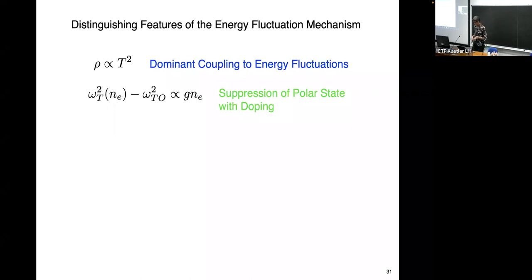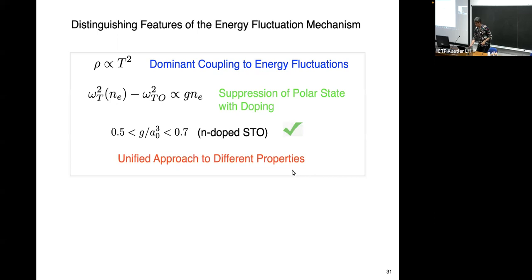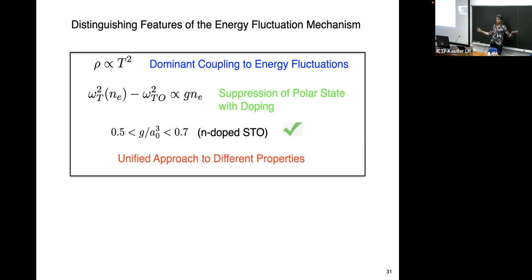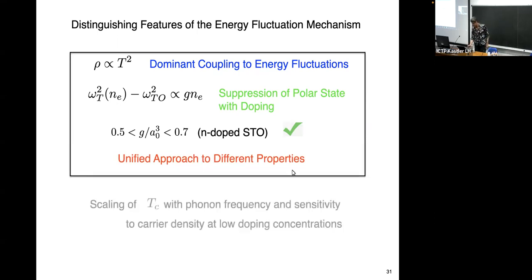One is that rho goes like T squared, the dominant coupling of the electron to the energy fluctuations. I should say there's still some mystery at low temperatures, but for a very large temperature regime. The second is that we have suppression of the polar state with doping. And in all of these cases, we have a G over A0 cubed that goes from 0.5 to 0.7. So it's a unified approach to very different properties of this material.